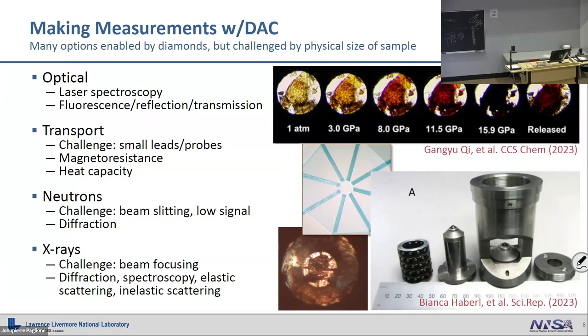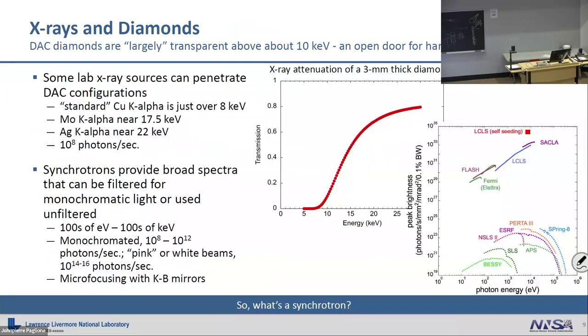And then there's X-rays. The nice thing about X-rays really comes from the synchrotron. X-rays were always good in a lab source. They work with diamonds. But the real revolution in diamond cell characterization came about with the third generation light sources that we'll talk about. So why is that so important? Unlike neutrons, scattering in X-rays goes as Z squared. So the bigger elements scatter better, and light elements scatter poorly.